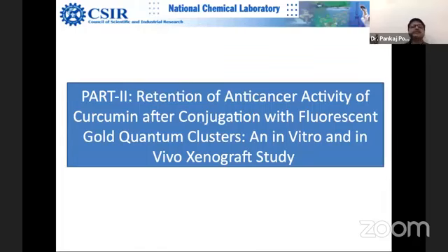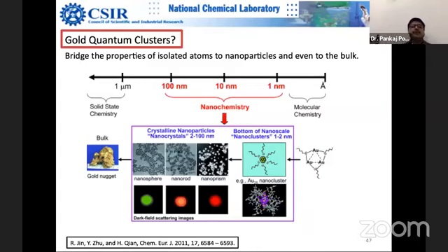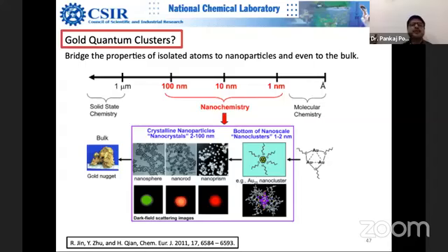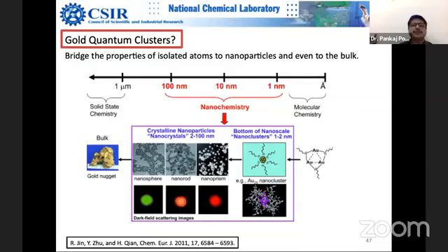We discovered that we were getting a significant concentration of what we call quantum clusters. Quantum clusters are essentially the last frontiers of material science — particles below the nanoscale. They have no fixed lattice structure. If you add or remove one atom, the electronic properties undergo tremendous change. These are not as systematic as nanoparticles. Nanoparticle physics is very predictable, but quantum clusters are quite unpredictable because almost all atoms are at the surface. They are very challenging systems. In the quantum cluster limit, gold starts fluorescing — normally gold does not fluoresce and shows metallic properties. It took us a long, long time — it was basically a headache at first, but then we thought it is a blessing.